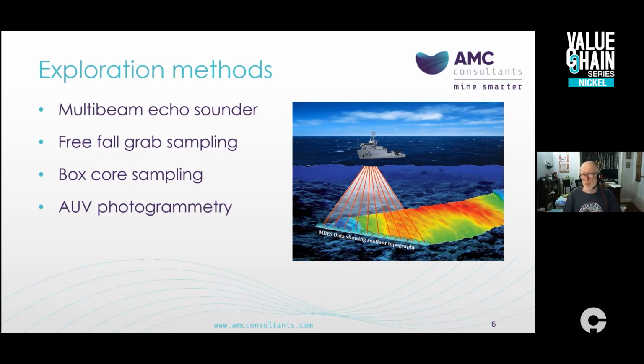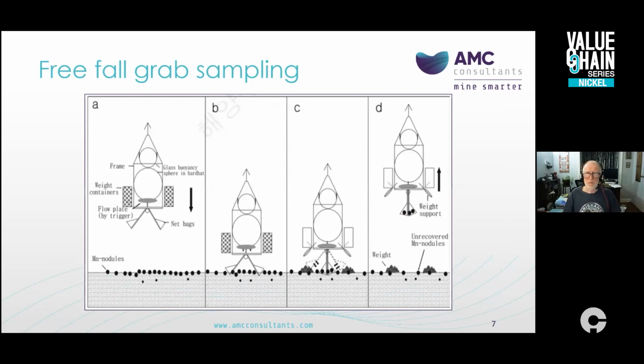This is done by taking samples from the seafloor using a free-fall grab sampler or a box core sampler. The weight of the nodules collected divided by the area from which they were collected is the abundance of the nodules in kilograms per square meter. Autonomous underwater vehicles, or AUVs, are often also widely used. They're operated a few meters above the seafloor to collect detailed quantitative photographs of the nodules and to map the geological and topographic features that may influence the formation or preservation of nodules or impact the way that they can be recovered. We'll look at each of these methods in a little bit more detail.